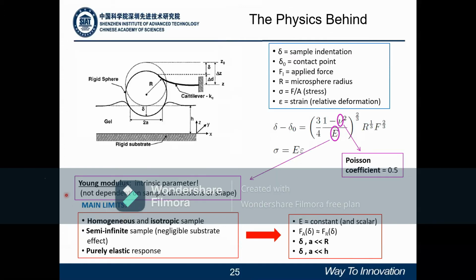So here is the physics behind the Hertz model. By measuring the indentation of the sample and the corresponding reaction force, it's possible to retrieve the Young modulus, also knowing the Poisson ratio. The Young modulus is an intrinsic parameter of the sample. In this case, there are some limitations: the sample must be homogeneous and isotropic in all dimensions, plus it should be semi-infinite. It means that the distance between the surface of indentation and the rigid substrate should be large compared with the indentation, as well as having a purely elastic response.